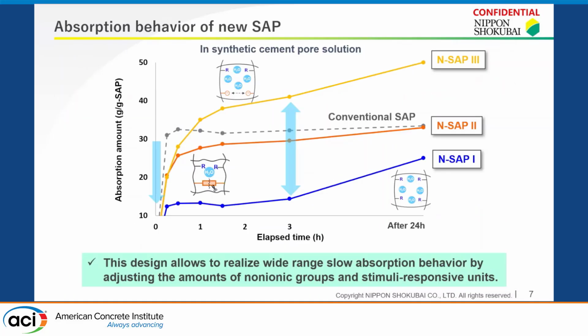This slide presents the absorption behavior of new SAP in synthetic cement pore solution. This graph shows the relationship between time and the amount of water absorbed by different types of SAP. We have 3 examples of new SAP based on our new concept. New SAP 1 contains only nonionic groups. On the other hand, new SAP 2 and 3 incorporate nonionic groups and stimuli-responsive units. As shown in this graph, the initial absorption amount of new SAPs is lower than conventional SAP.